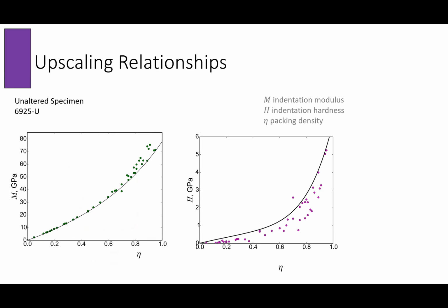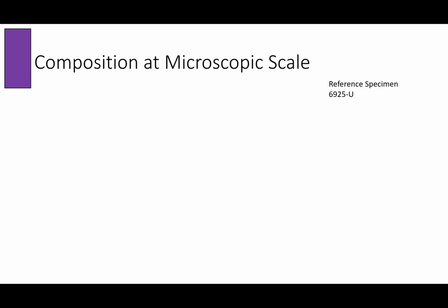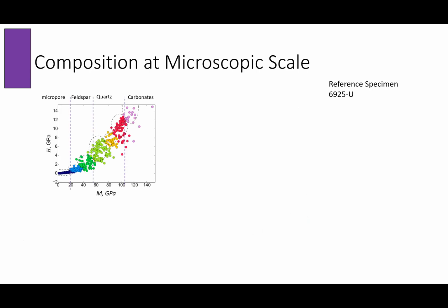And that's kind of an example of what it looks like when you want to go, for instance, from the sub-nanometer level to the nanometer length scale using indentation. What is really good is that we are able to really map the behavior. So if you look at a reference sample that is unaltered, after conducting scratch tests, we are able to identify different mineralogical groups. So we have micropores, we have feldspar, we have quartz, and we have carbonate.